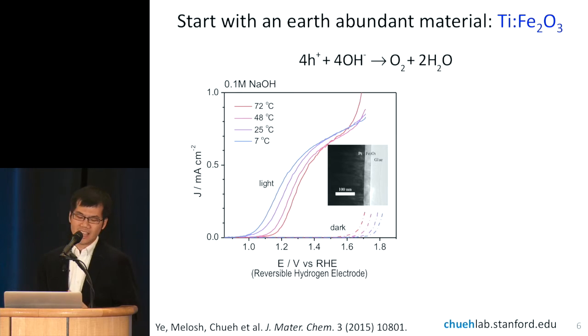to the left, but instead what we see is as we crank up the temperature, the curve is actually shifting to the right, which means that the driving force is decreasing. So this was a bit disappointing, and moreover, if you look at what is called the saturation photocurrent, it is also not changing with temperature either.